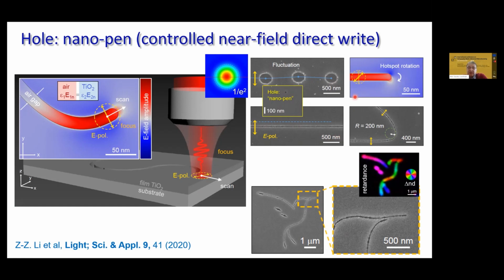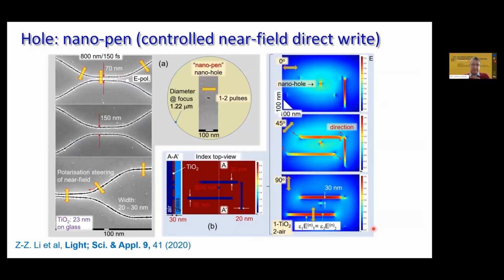There is also a possibility to steer the direction where you write. So if you change polarization orientation, you actually steer the tip of the intensity distribution into the direction you want. And this way, by changing polarization, you can turn very sharp corners and write an ablation groove which is really on the scale of tens of nanometers. And you can write those nanogrooves very closely.